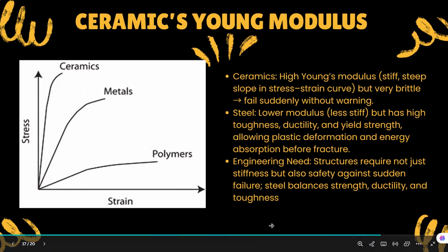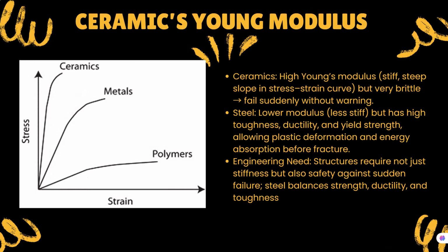And here, the question: why does ceramic have a bigger Young's modulus, but it easily fails? Because the behavior of ceramics is very brittle. It is stiff, with a steep slope in the stress strain curve, but very brittle. Compared to steel, which has a lower modulus, so it is less stiff, but has high toughness, ductility, and yield strength, allowing plastic deformation and energy absorption before fracture. While for ceramics, there is no plastic region, so it easily fractures. In engineering, a structure requires not just stiffness but also safety against sudden failure.